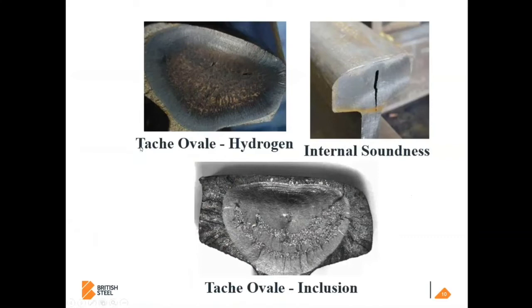So this type of fatigue crack here in this rail break is called a Tache Ovale. It's a particular type of fatigue crack defect, which is from an internal stress raiser, and it's fatigued from the inside out. So this one is from shatter cracks from hydrogen. There's a little hydrogen crack there, and then you've had this fatigue crack grow, and it's grown to quite a large size, actually. It speaks well of the steel that it's got quite so large before it's brittle failed.